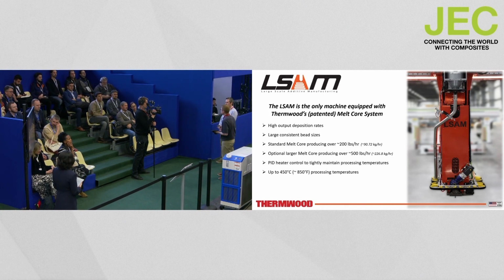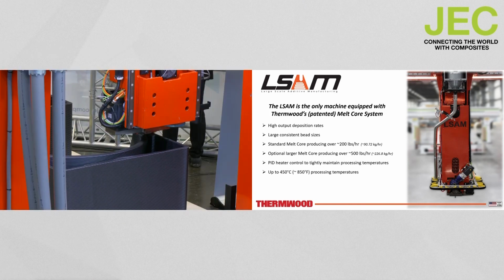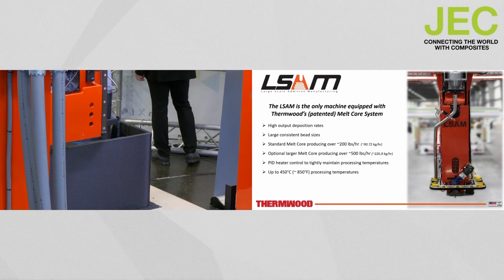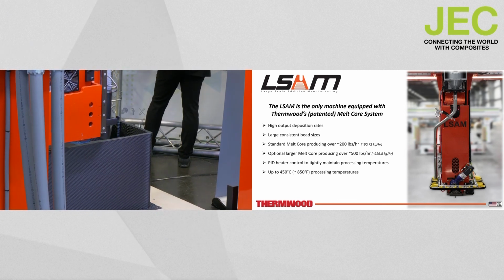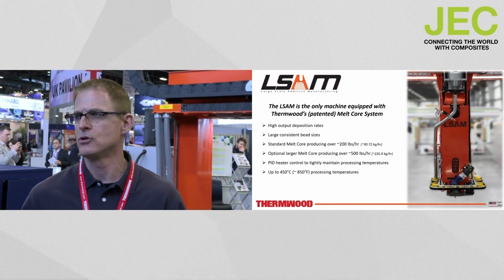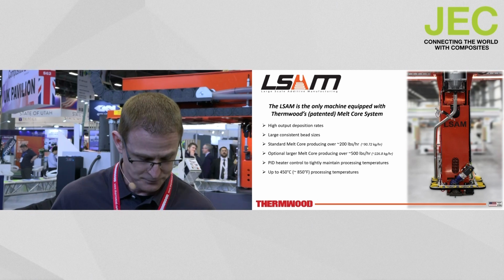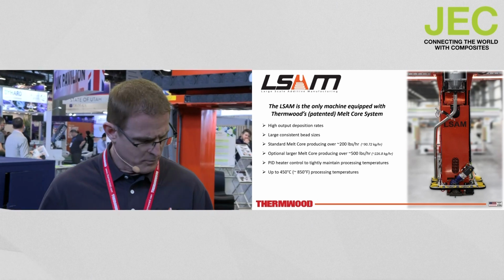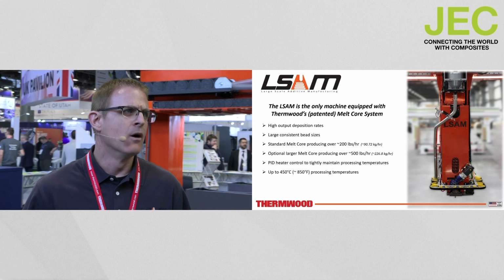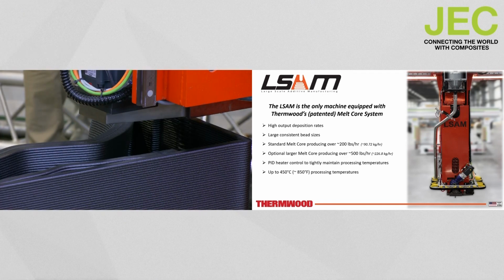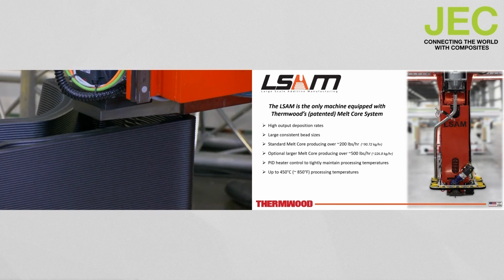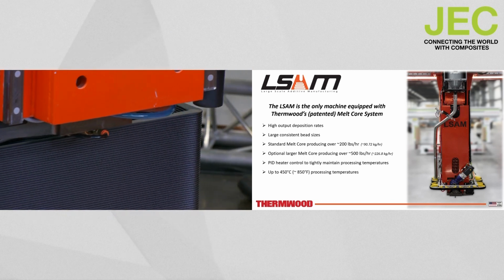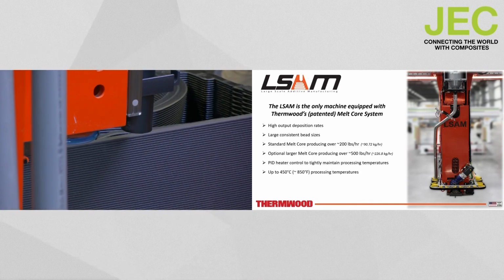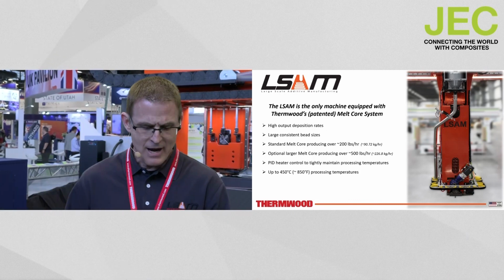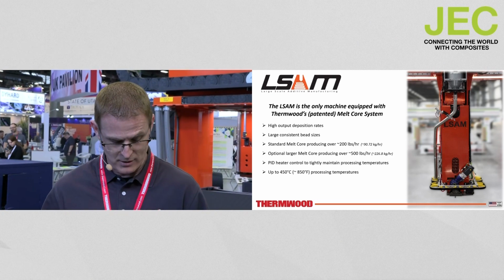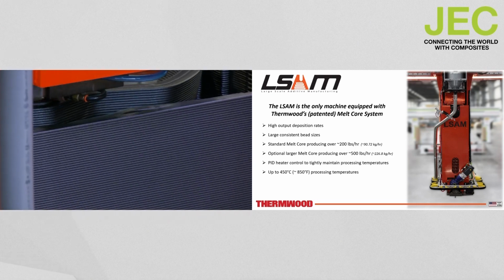First, the LSAM is the only machine equipped with Thermwood's patented melt core system for processing materials. This melt core is designed for high output deposition rates to produce large, consistent bead sizes. Our standard melt core produces over 200 pounds an hour, or about 91 kilograms per hour, and our optional larger core produces over 500 pounds per hour, or about 227 kilograms an hour. It utilizes PID heater control to precisely maintain processing temperatures up to 450 C.